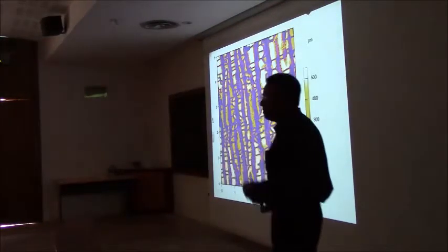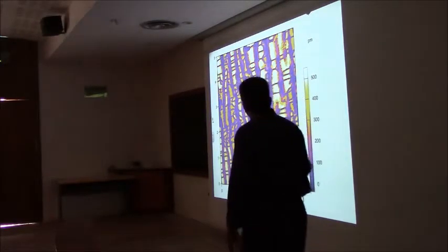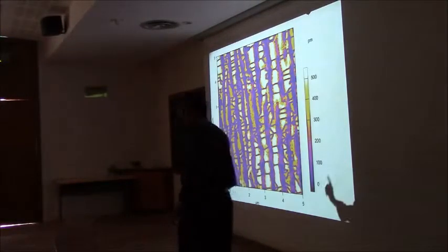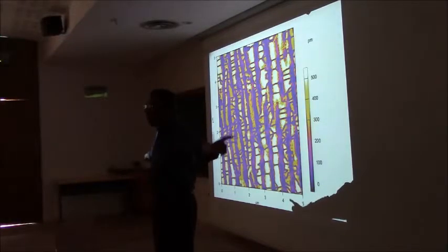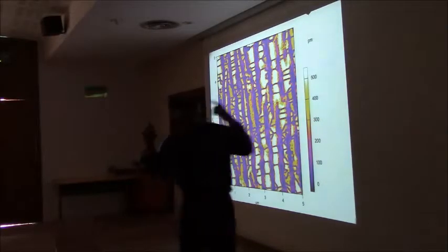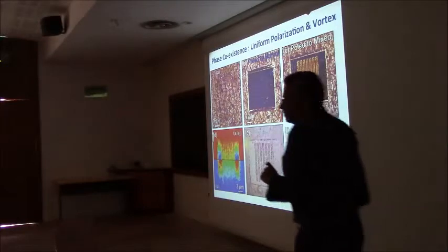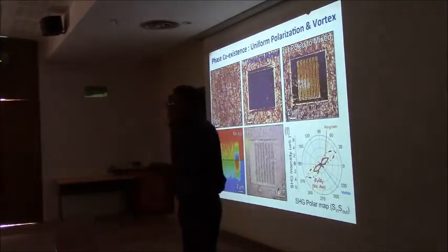I'm going to show you a doctored image. This is the similar kind of image, but we artificially jacked up the intensity to see. This is the ferroelectric phase, and you can see these domain walls here, but in all of these, they go right through the vortex phase. So this is the first indication that we had that the vortex phase itself can have 2 different polarization vectors. There could be a domain wall in the vortex phase, and it's something that we are pursuing. So quite complicated.